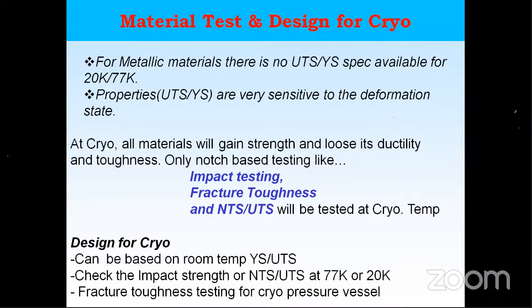But the same specimen, if I take it to low temperature, 77 K, that's LN2 temperature, I get different values, because a small defect or a small discontinuity or any defect present in the gauge length can alter the value. Even carbon in an industrial amount, if locally present, can change the value. So the properties of UTS and YS are very sensitive to the defects as well as the deformation state. Suppose I do some cold work or elastic deformation and test it, then also the value changes. So I don't have a fixed value.